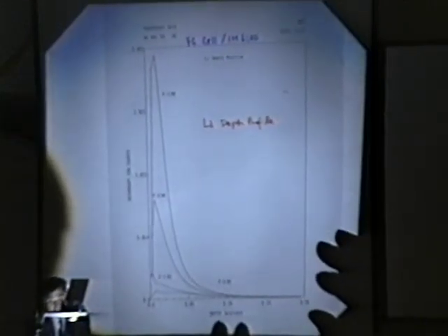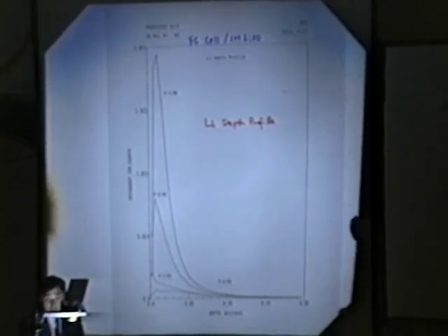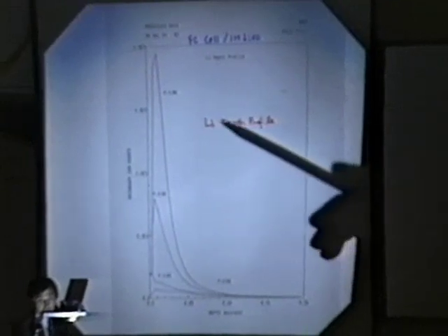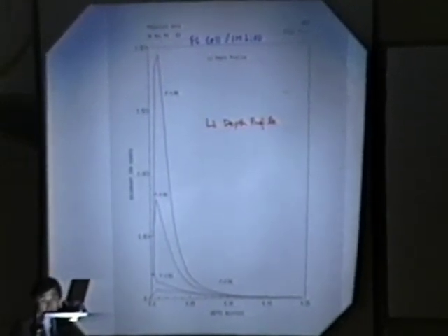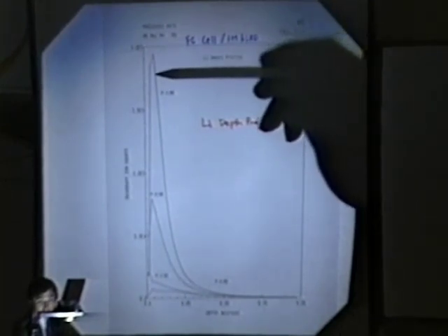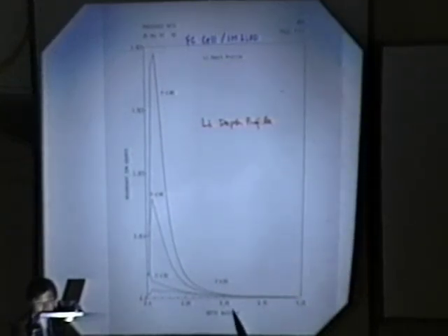And we have also conducted lithium analysis, a similar SIMS analysis, which was originally done first by Professor Okamoto and then Professor Ota in Japan. And our data showing the depth profile is very similar to those reported by Professor Okamoto and Professor Ota. So the lithium is very much concentrated on the surface and then goes down very quickly, when the distance is something like 0.1 micron.